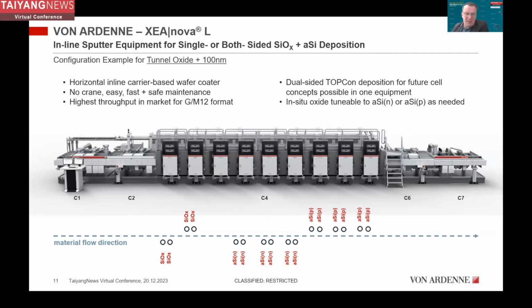So if you see this slide, you can imagine that you can use all of the TOPCon coating in the same equipment, not only for the rear side, but also from the front side. So you can apply the coating units for the tunnel oxide, in this case, for the rear and for the front side, then you apply a gas separation, and then you finish the rear side polysilicon coating and the front side polysilicon coating, and then you have a double-sided TOPCon device. For sure, you have to apply structuring processes there, but there are smart solutions out there to apply it. And you can imagine also to use this configuration, maybe to just use sputter down processes and to do the coating of the rears of the IBC structure also in one device.